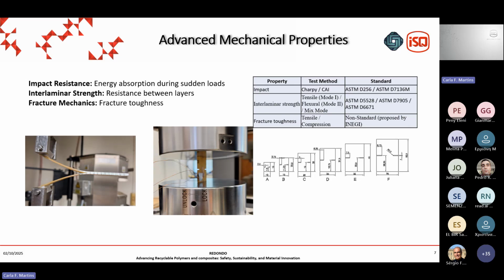So what I depicted here is a procedure for polymers and especially composites that was developed. It's not a standard method, developed at INEGI in Portugal. INEGI is an institute associated with the Faculty of Engineering of Porto University, and involves the testing of 6 different specimens, which are normally called double-edge notch beam specimens because they have 2 notches in opposite edges, and to test 6 different specimens, increasing dimensions, both in tensile and in compression, to determine what is called usually the resistance curve of that material. So which is a measure of their fracture toughness.